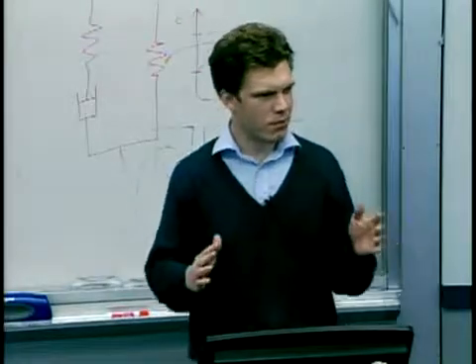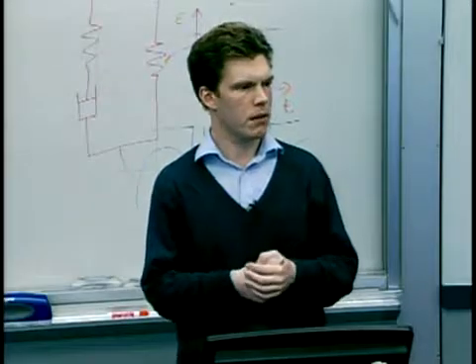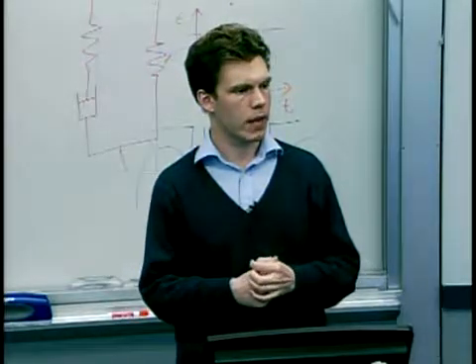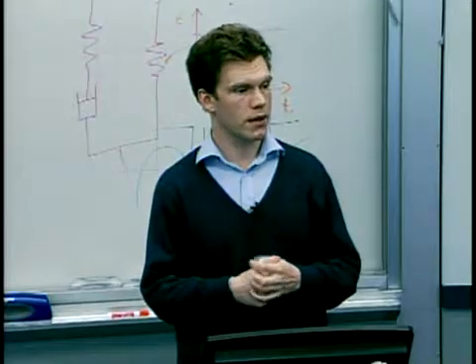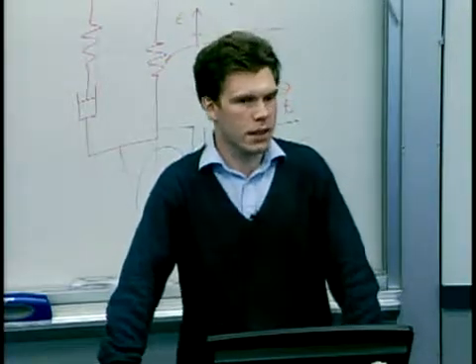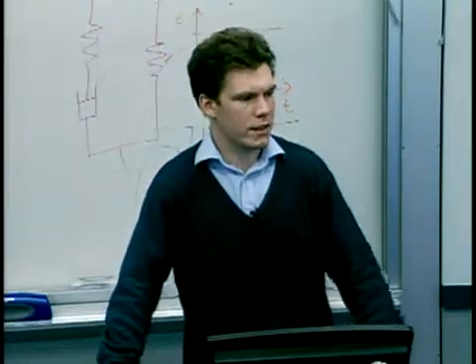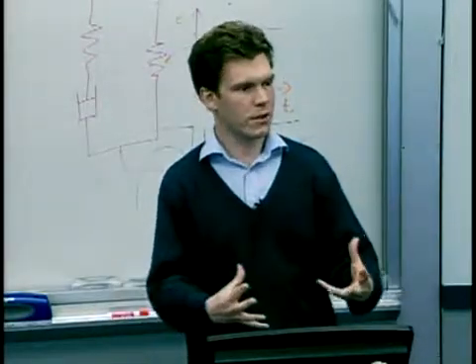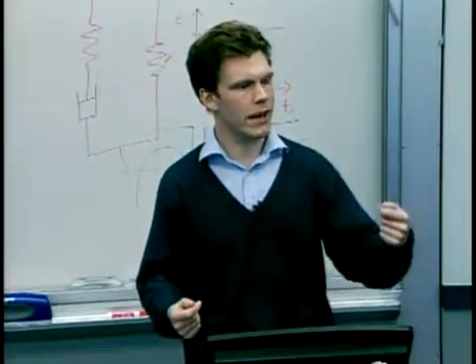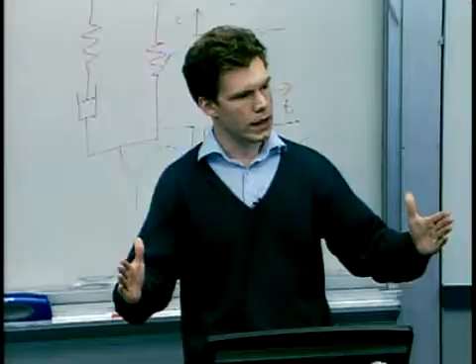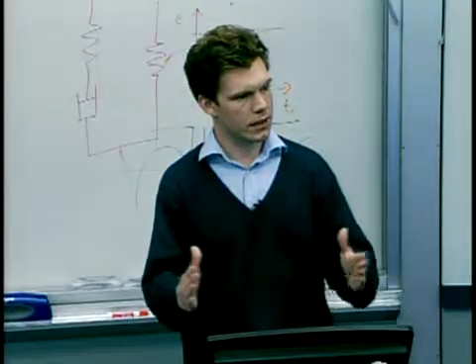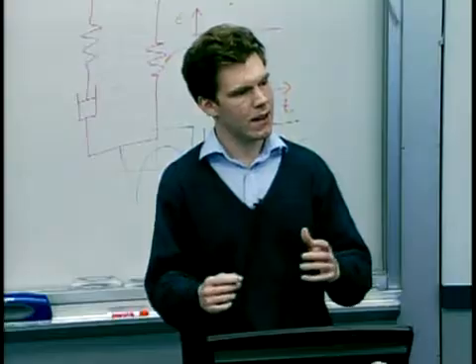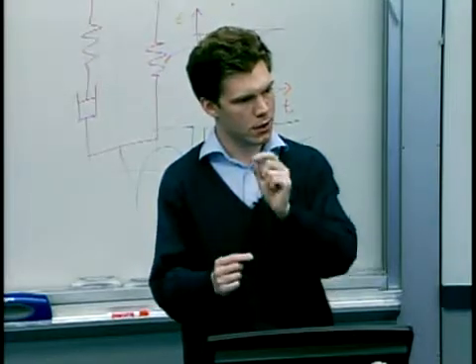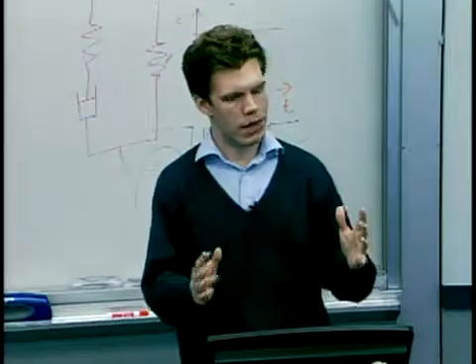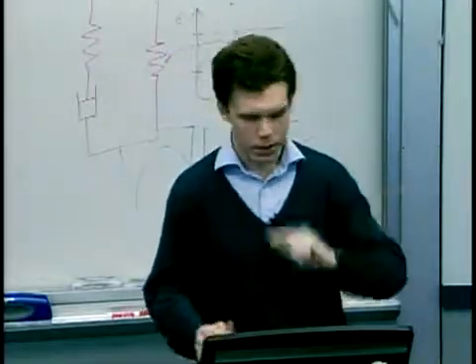I mean, actually the compressive stresses experienced by the silicon are nowhere near enough to break it; the tensile strength of silicon is over 100 megapascals. But actually, where the danger arises is when you're cooling the substrate, and we'll get onto that. But it's really the lateral forces applied to the protruding stamp features that are dangerous, because they create moments on the features and can cause cracks at the base of the feature to propagate. So, a good question, right?